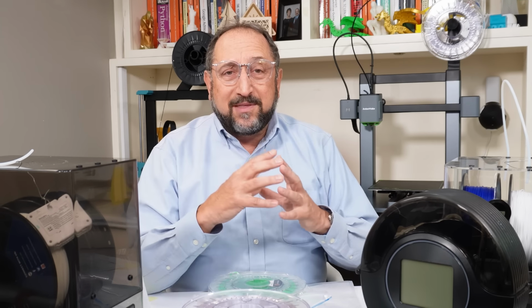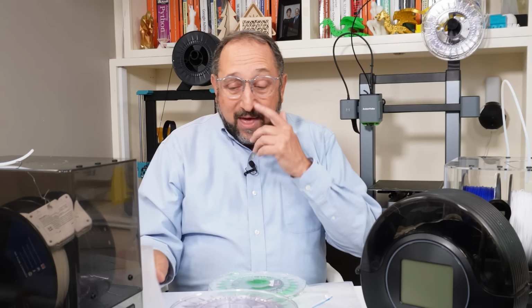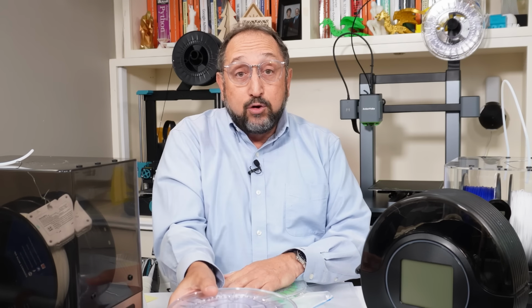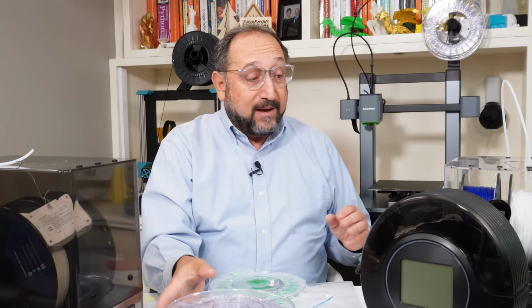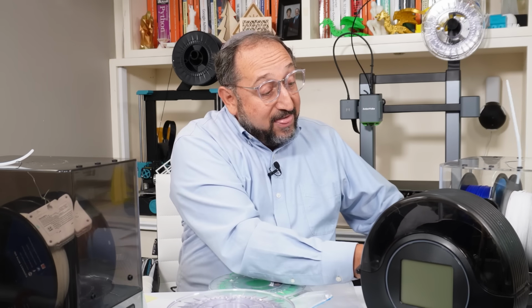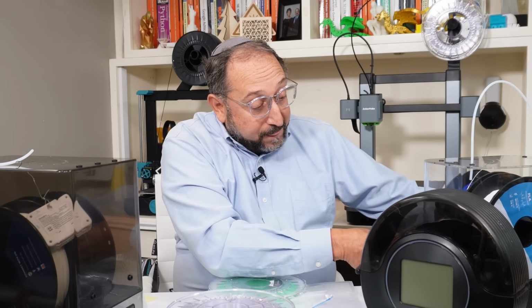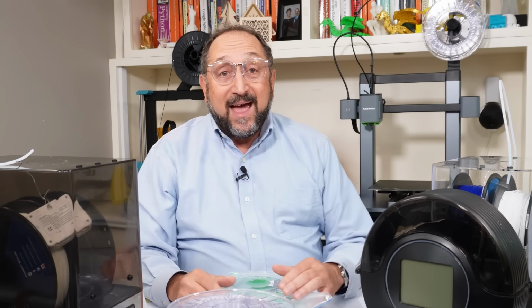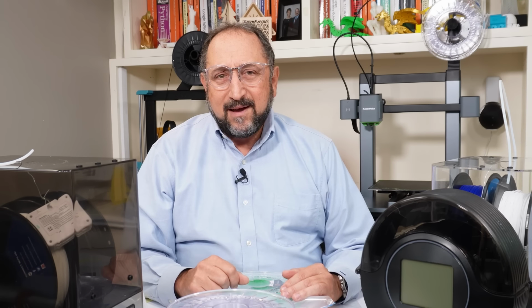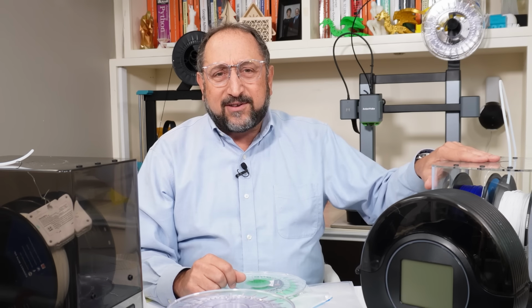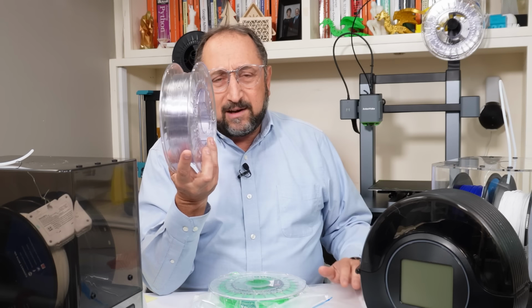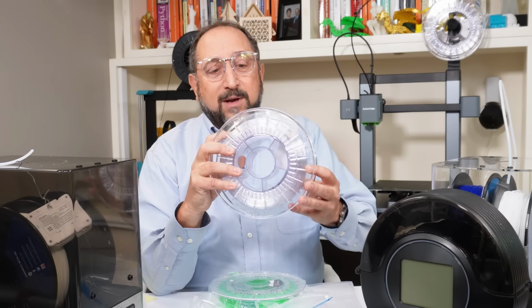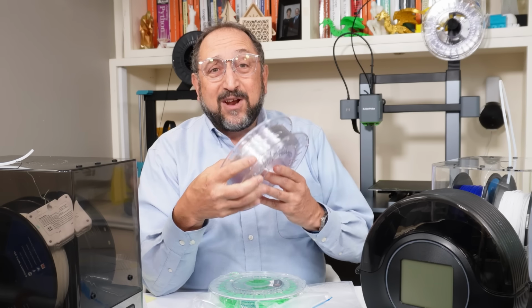So how did I diagnose this problem? Well, the first thing I did is I happened to have another reel of ColorFab XT, and I went to print with it, and it was just fine. So then I thought I'd dry out my reel of ColorFab XT. And at the time, I was using this particular print dryer, which is made by a company called Eibos, and I was a little naive. I set the print dryer to 70 degrees Celsius because this print's at a relatively high temperature, and I went to dry it. And I left it overnight.